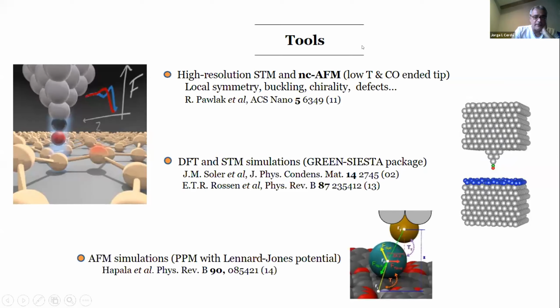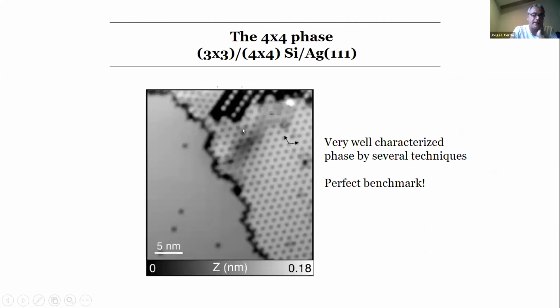And finally, to simulate the AFM images, we've used the particle probe model that was developed in the group of Pavel. It is very simple, very fast, extremely simple compared to an STM simulation at the ab initio level. Here we use very simple Lennard-Jones potentials, but as you will see, the agreement is great. I was really impressed by this program, which I simply downloaded. I think it's a great success for the simulation community. As I say, the simulations are extremely fast, and you will see that the correlation with the experiment is very nice. So we'll start with the 4x4 phase. This is the seminal work I showed you before.